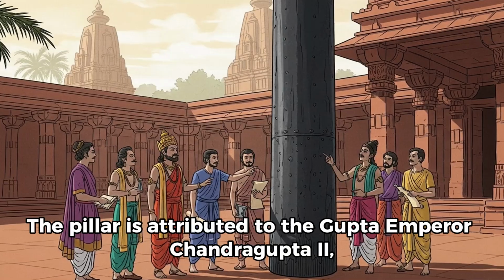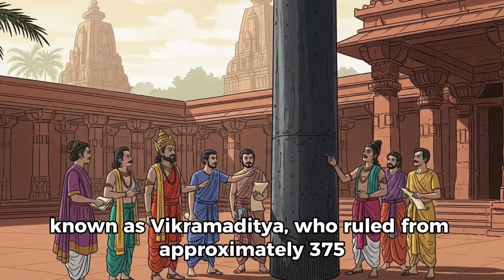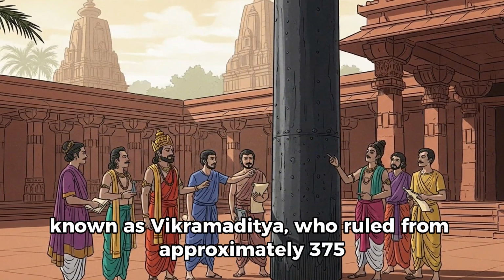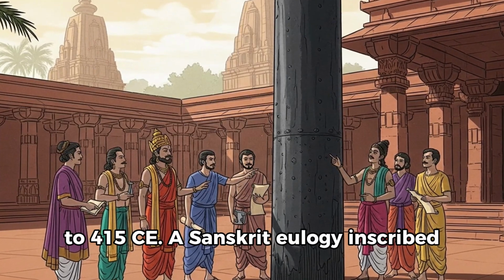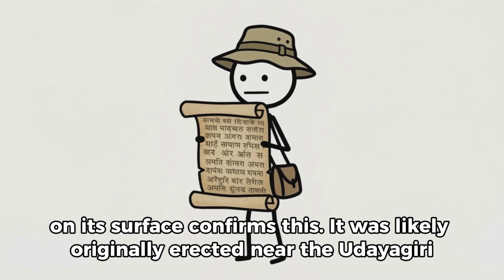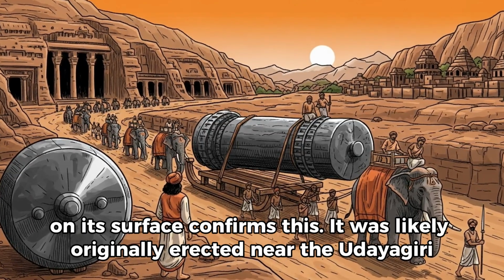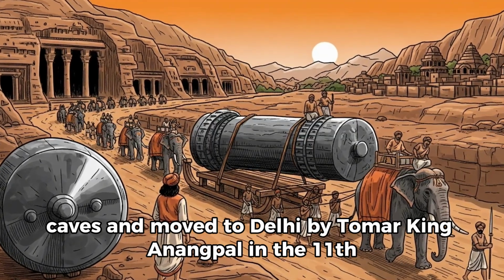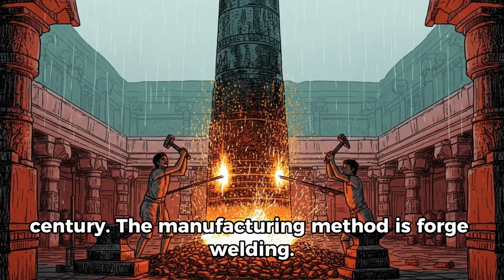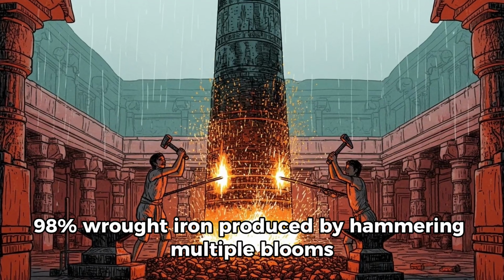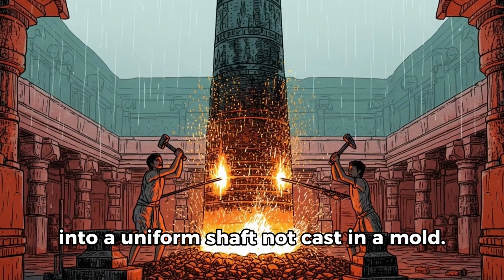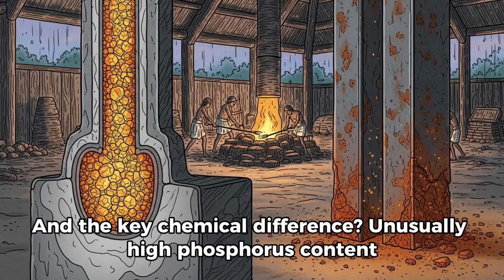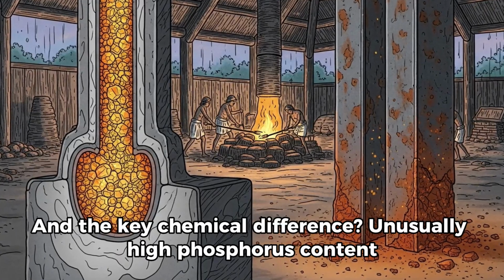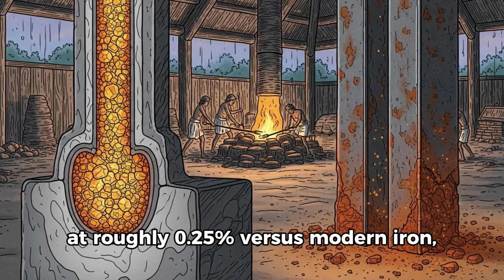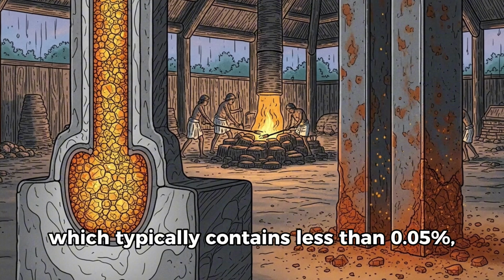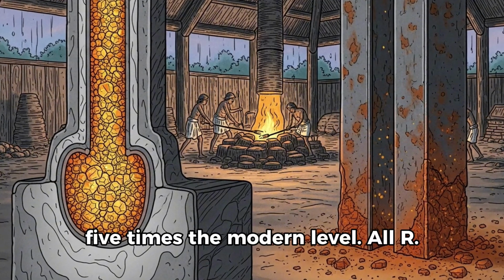It is not rusted. The pillar is attributed to the Gupta Emperor Chandragupta II, known as Vikramaditya, who ruled from approximately 375 to 415 CE. A Sanskrit eulogy inscribed on its surface confirms this. It was likely originally erected near the Udayagiri caves and moved to Delhi by Tomar King Anangpal in the 11th century. The manufacturing method is forge welding, 98% wrought iron, produced by hammering multiple blooms into a uniform shaft, not cast in a mold. And the key chemical difference, unusually high phosphorus content at roughly 0.25% versus modern iron, which typically contains less than 0.05%, 5 times the modern level.